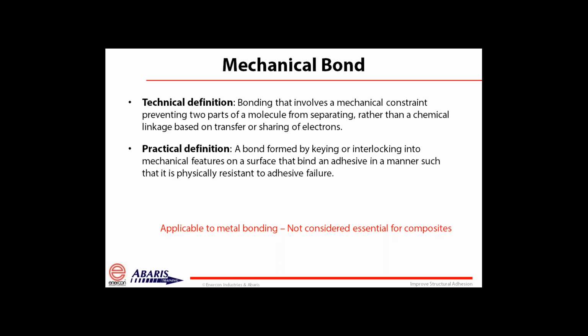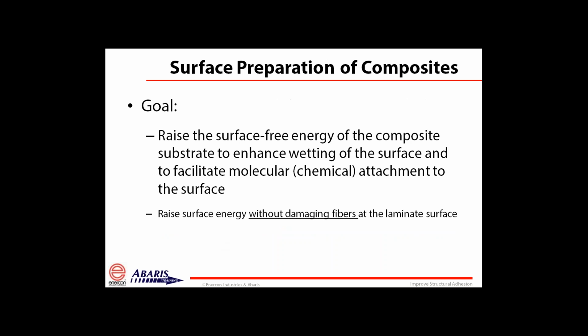Now, realistically, that can be done, but generally it is not done with composite materials because when trying to create some sort of mechanical surface, there's often a degree of damage that is done to the fiber in the underlying surface. Now, there's a big difference between the way a boat builder might approach a good bond compared to an aerospace or automotive person using composites. And so we do not recommend trying to achieve a mechanical bond, but a chemical bond with composite materials.